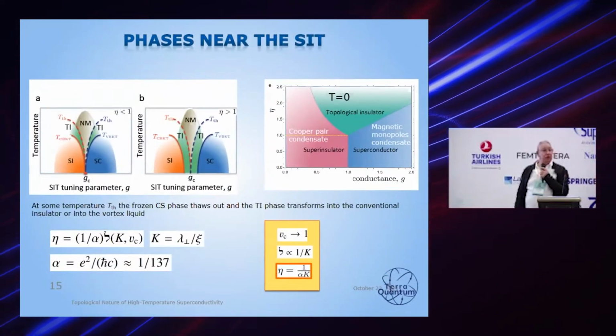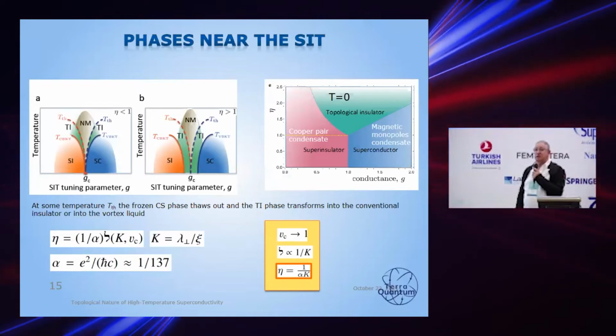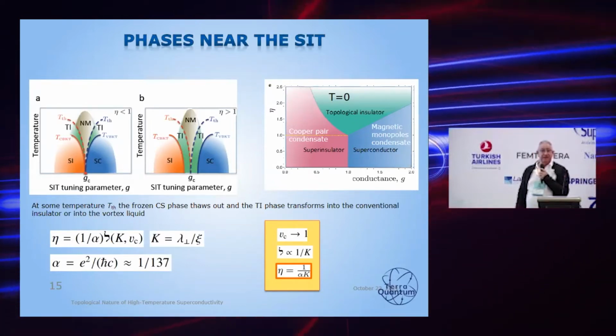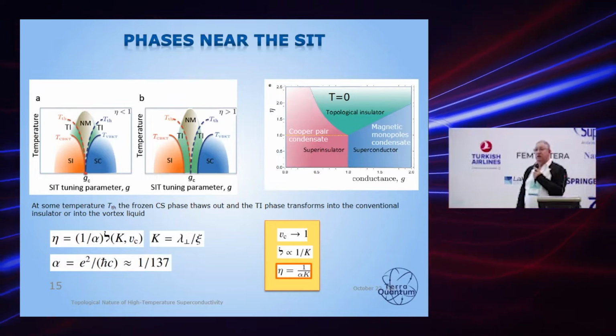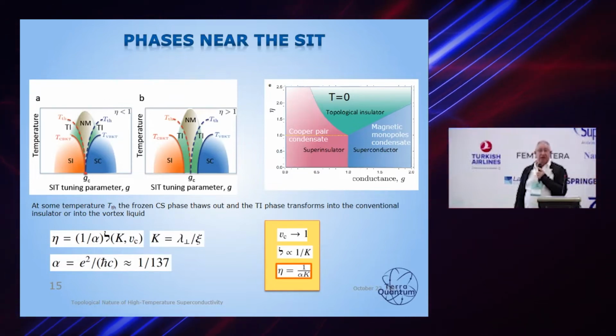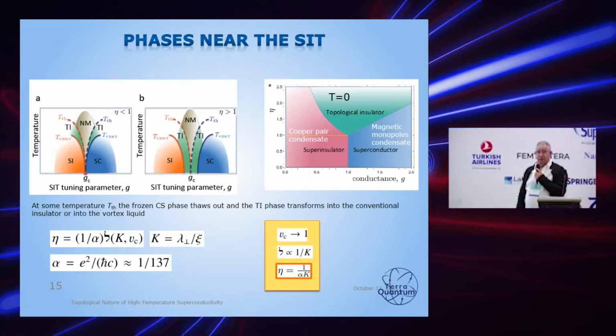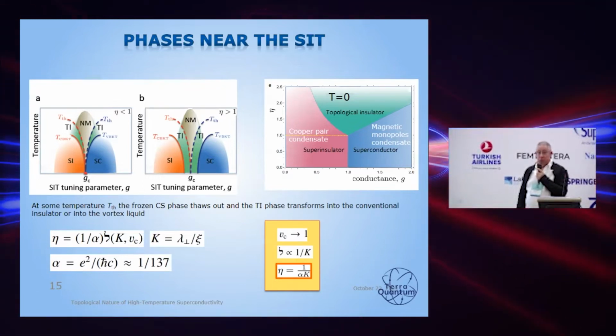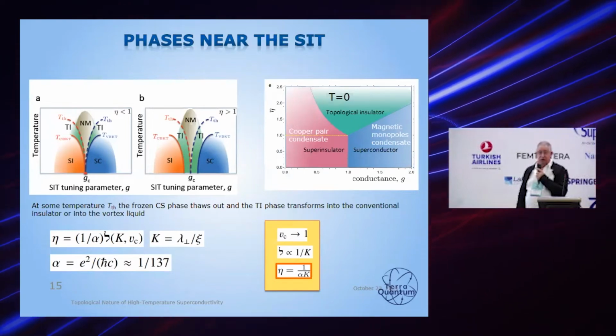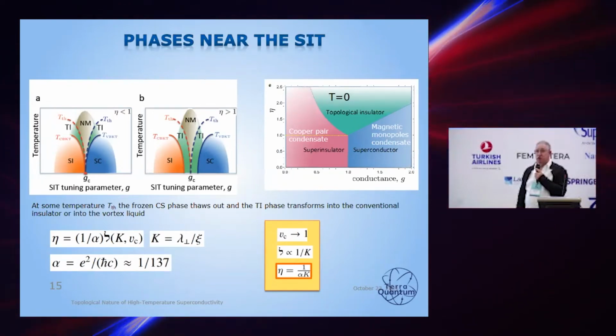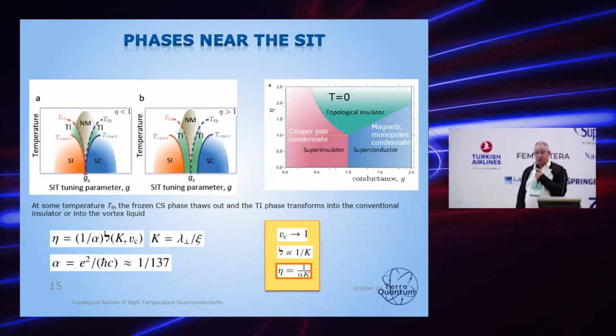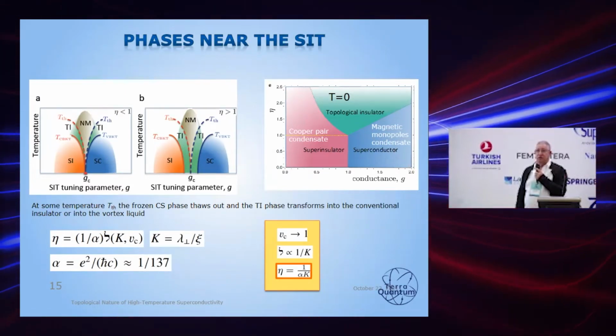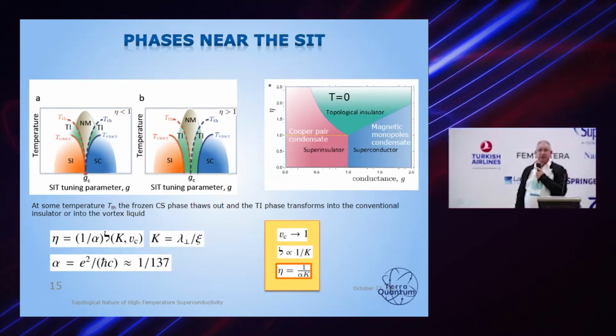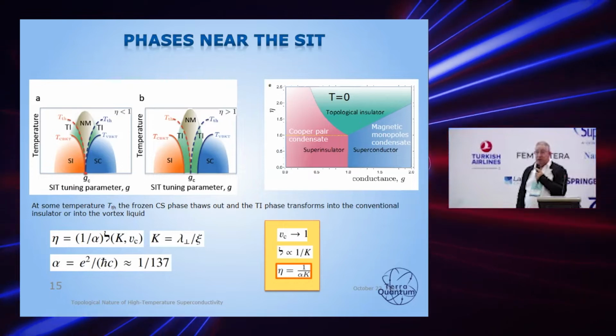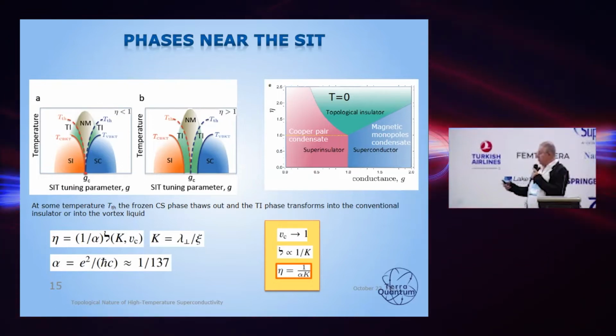One thing more, sorry, which I forgot to mention. If we do now the exact theory of the superconductor-insulator transition, then we can immediately see that instead of the duality Cooper pairs-vortices, the true duality is the Cooper pairs-magnetic monopoles duality. So in a superconductor, we have a Bose condensate of Cooper pairs, but in a superinsulator, we have a Bose condensate of magnetic monopoles. Then our electromagnetic symmetry is full, and this is the full description of the superconductor-insulator transition.